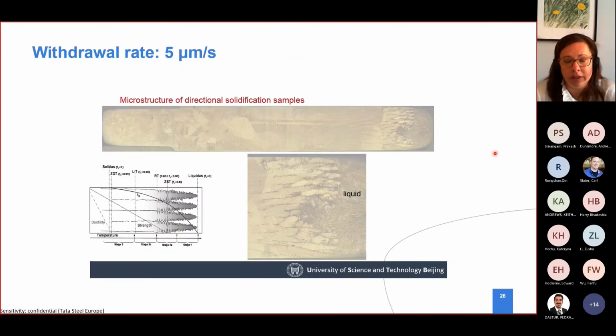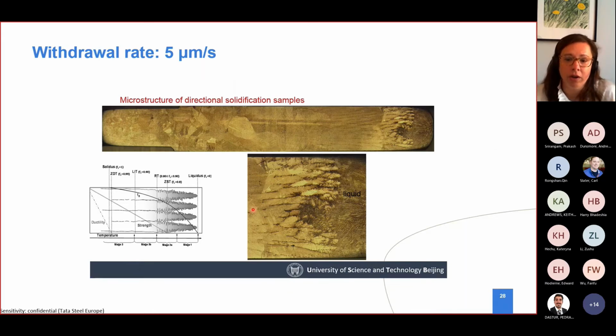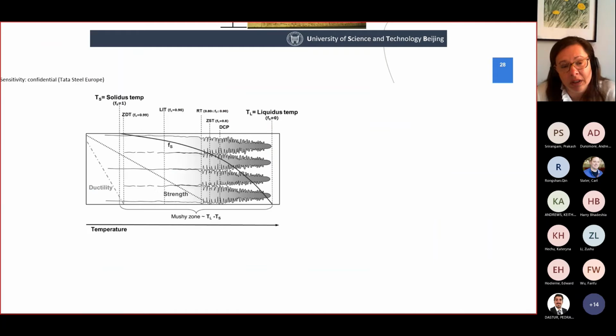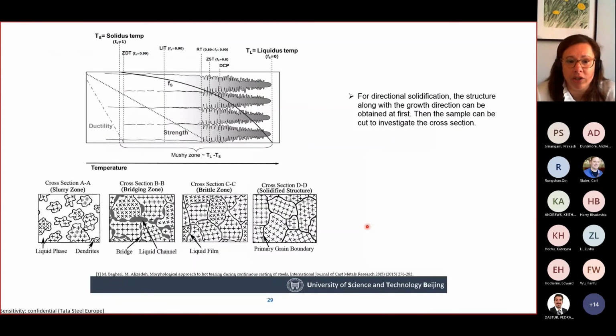Why is it so important? If we follow the microstructure, knowing and quenching it at a certain moment, we can directly relate that with different important temperatures related to the solidification of a particular steel. The sample is small, but with this directional solidification, if we quench it and cut it in different slices, we could also follow how the segregation happened, and how the liquid and solid phases appeared here.